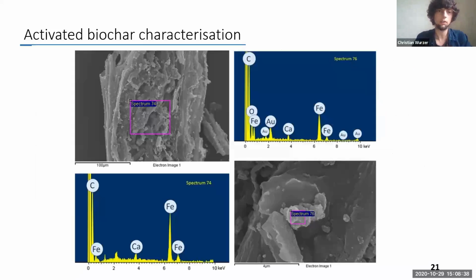To have a look at how magnetite on a biochar looks like, here you see again the softwood biochar with 10% ochre addition in a SEM image equipped with an EDX scanner. So we see in the spectrum that these are magnetite, not from this spectrum, but from the XRD we know it's magnetite.